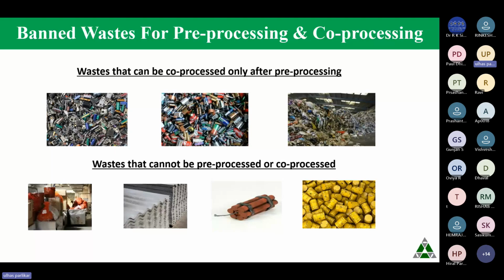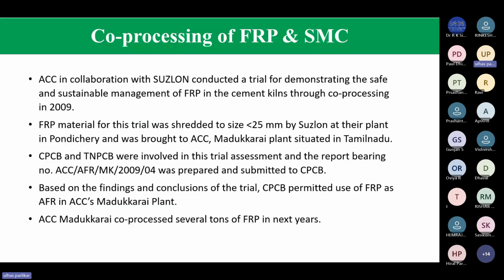So ACC, I told you, in collaboration with Suzlon, conducted the trial for demonstrating the safe and sustainable management of FRP in the cement kiln through co-processing in 2009. The FRP material for this trial was shredded to a size less than 25 mm because that was a requirement of that particular kiln. The shredding was done by Suzlon, and that material was generated in the Pondicherry plant. And then it was brought to the ACC Madukarai plant, which is situated near Coimbatore in Tamil Nadu.